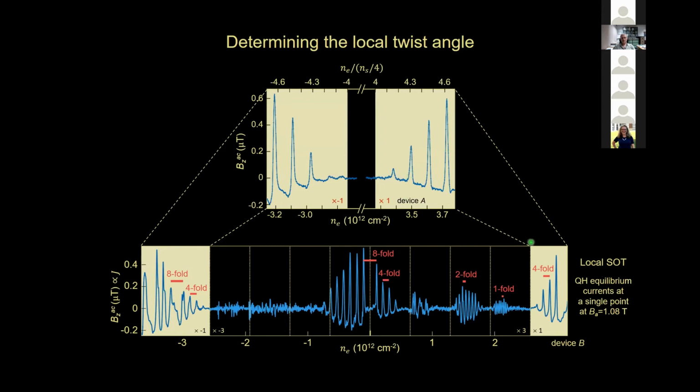So now let's focus only on these dispersive bands. These are the Landau levels in the dispersive bands, and as I said, they are 4-fold degenerate, so we know exactly the distance between them. But now if we measure the distance between this Landau level and this Landau level, the distance in units of carrier density will be the degeneracy of the Landau levels: 12 here and 12 here, so this is 24, plus 2ns, namely we have to fill all the flat band before we start filling the Landau levels in the dispersive bands.